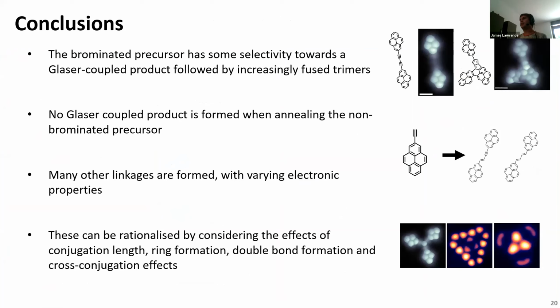So just a quick conclusion slide. We've shown how we've got a small amount of selectivity towards some products in particular with the on-surface chemistry of this precursor. In particular, we can only really form this Glaser coupled structure when we have a bromine attached to the side of the pyrene. We've shown how we can form lots of different linkages between these pyrenes with all of the different products we form, and we've tried to rationalize this in a hand-wavy way with things like conjugation length, ring formation, and so forth.